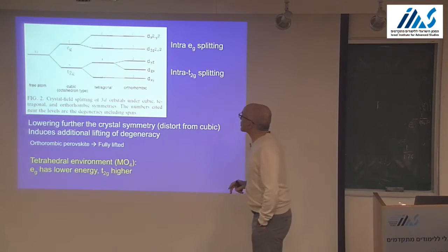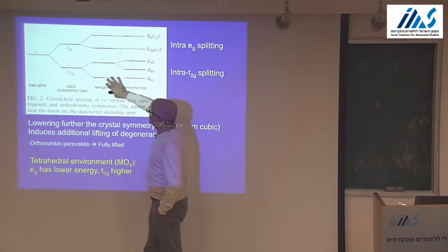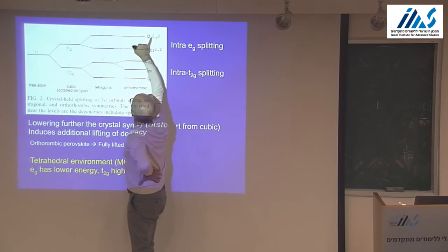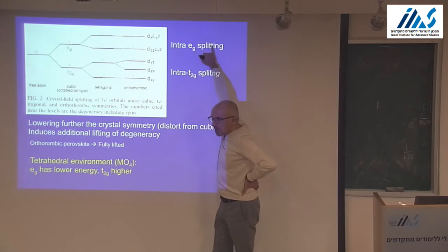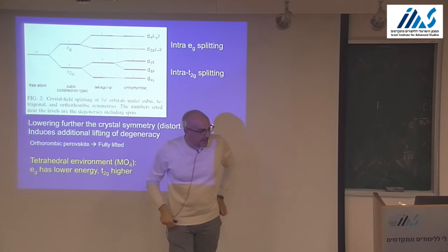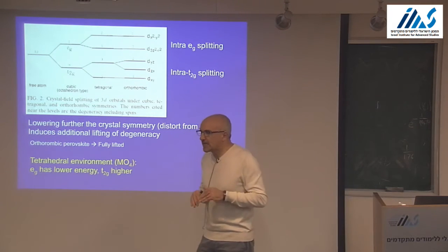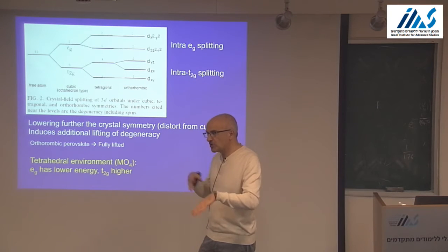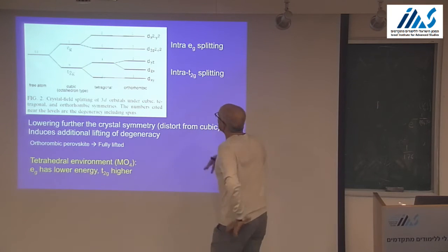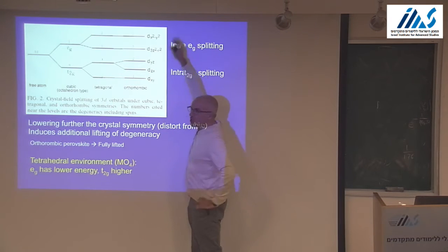Good question. So, of course, this is a crystal field diagram that takes into account the electrostatic energy of the oxygens. But this guy hybridizes with the neighboring oxygen orbitals. So when I said one band, what I really mean is that there is a combination, which is here the antibonding combination between x squared minus y squared and px and py, which form one band crossing the Fermi level.